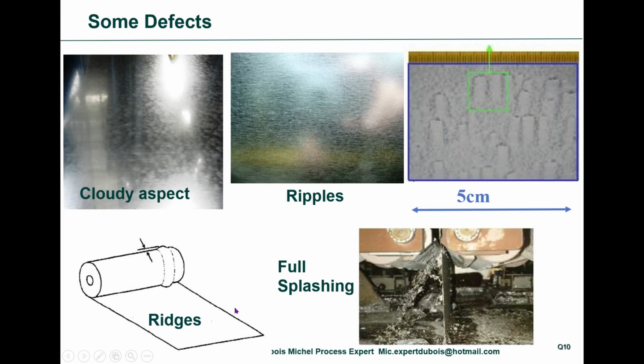The question of overcoating: it could be on the edges, but it could also be in the center of the strip. For example, in case of nozzle clogging, it's going to make a ridge. And why is it like that? Because you have overcoating. All that overcoating piles up during rewinding of the coil, and unfortunately the final customer never complains about variation of coating weight, but complains about strip flatness, because as soon as you decoil, the strip will be more deformed at that location and make waves.